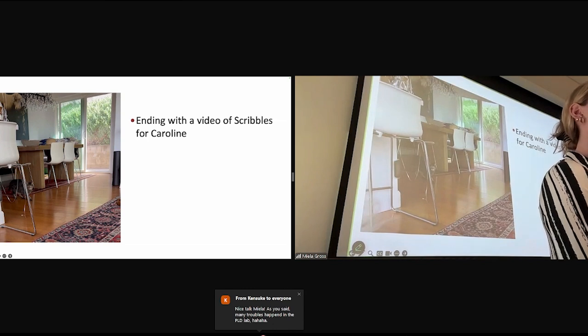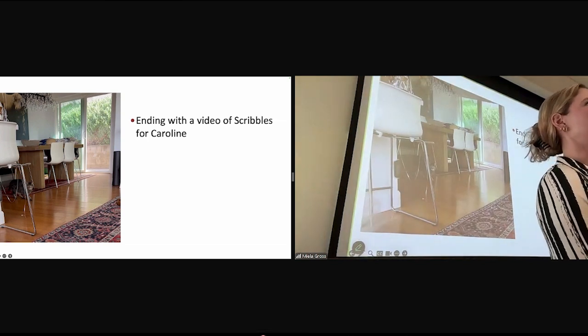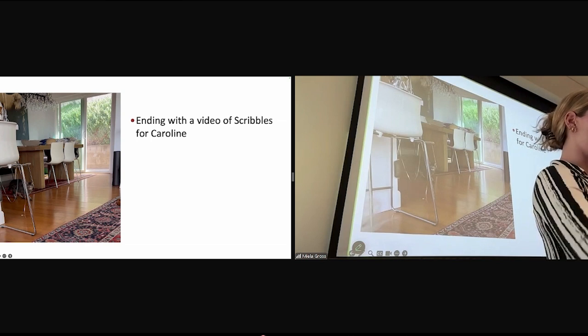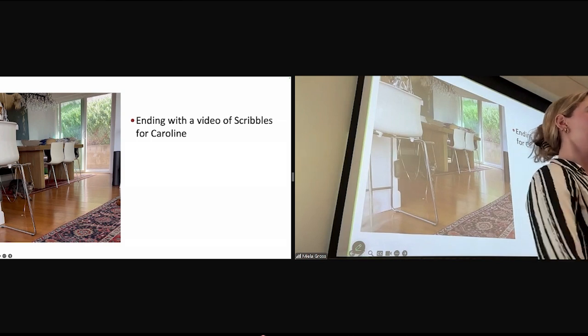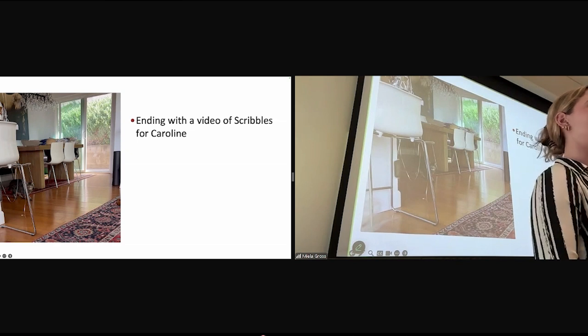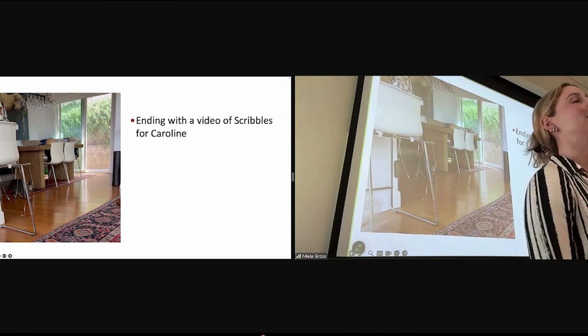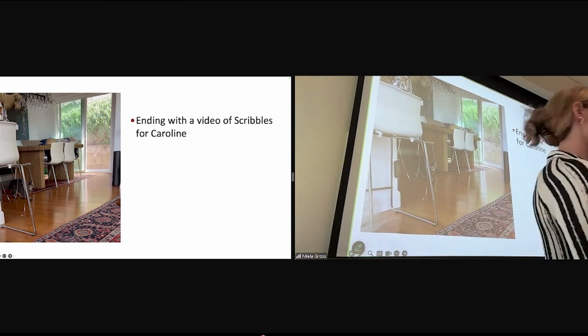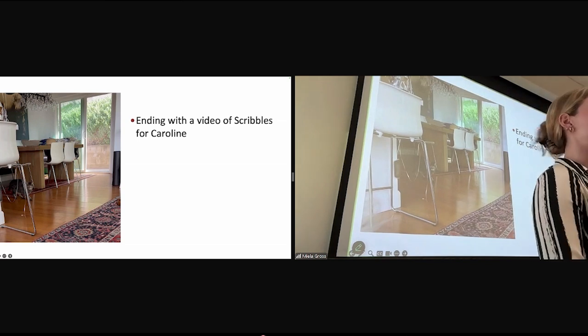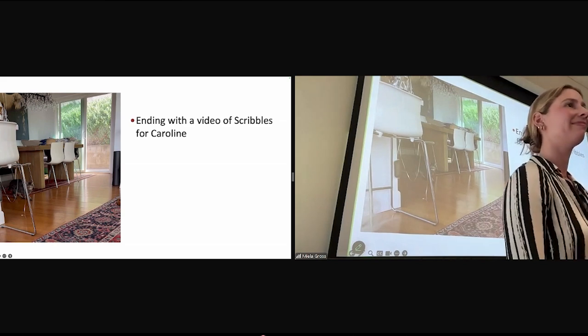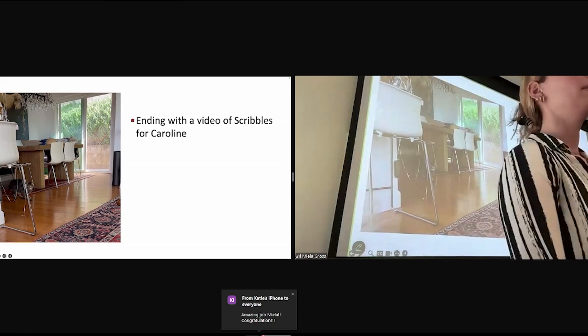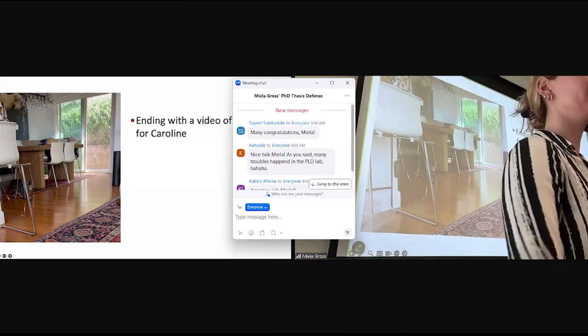Do the domain walls have durability, or do they last long? It's technically not even a particle. It's just the change in the magnetization. So the actual properties of the domain wall are inherent to the magnetic material that you're studying. If you turn off the switch, it just stays where it is. That's again dependent on your material properties, on however your magnetic material is engineered.